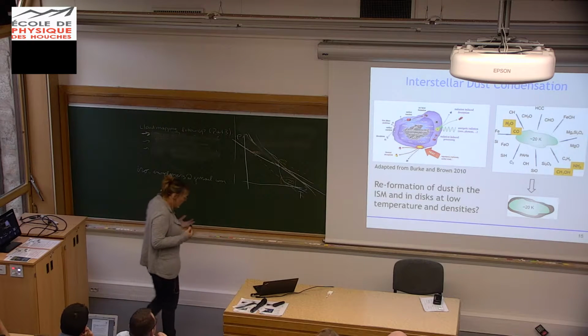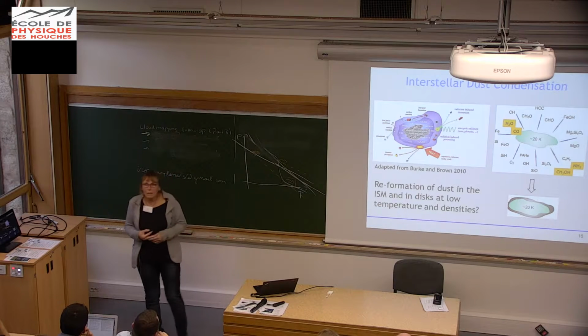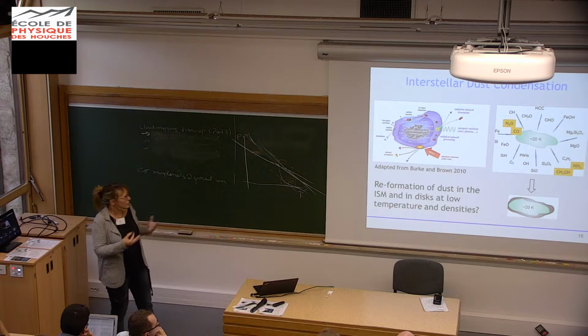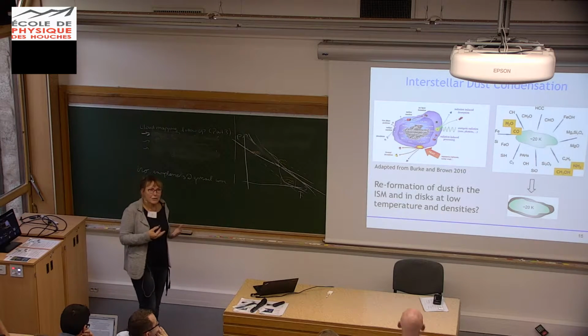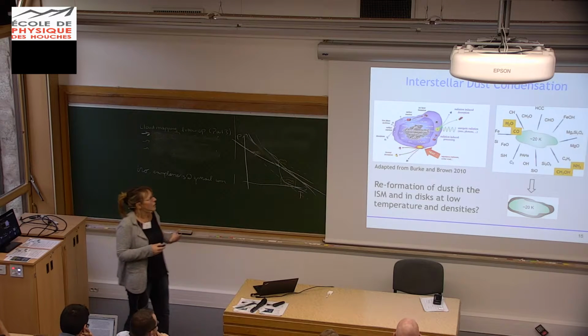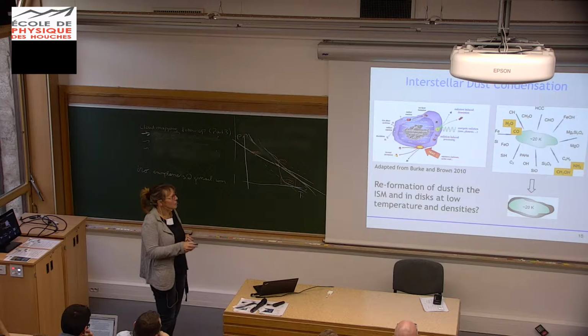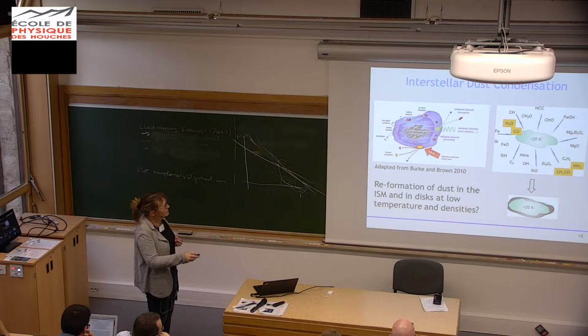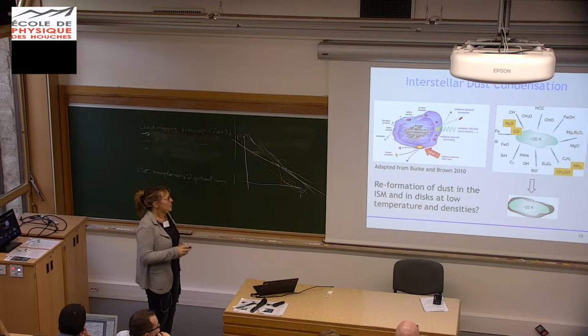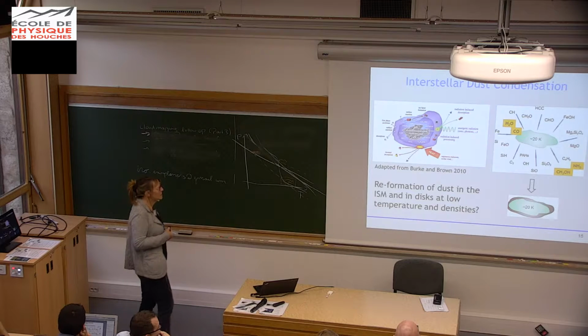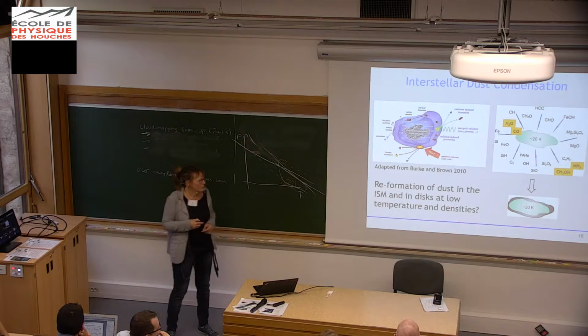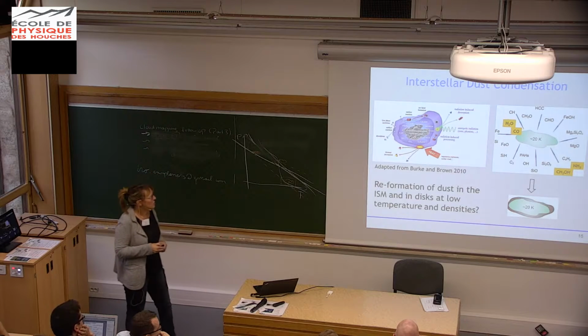However, it's also known that shock waves destroy the dust grains which were formerly produced in AGB stars. So also refractory species should be deposited or accreted onto these ice shells, like I have shown here. Apart from the normal gases, you have probably also something like FeO, FeOH, something like CH, CHO, SiH, and so on - refractory species which can somehow contribute to the condensation of silicate or carbonaceous material.